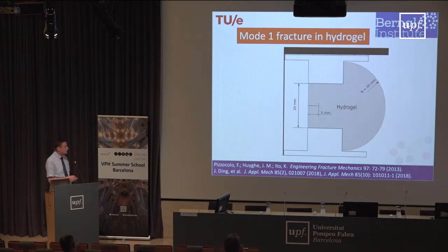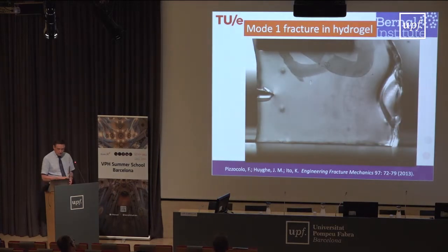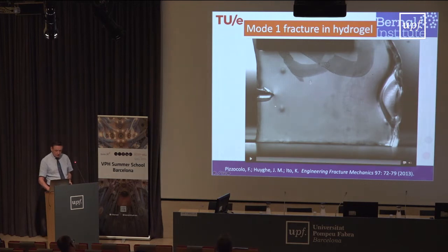An experiment relates to a gel. And the nice thing about gel, you can look inside it, which almost you never can do in a solid. But here you can look inside it. And we have a piece of gel with a small crack initiated in it, fixed on both sides to a drawing bench, the grips of both sides of the drawing bench. And you're going to move apart one side compared to the other and observe the cracking inside the hydrogel as it propagates. And so this is the gel. You see the initiating crack here. And we're moving apart the jaws.